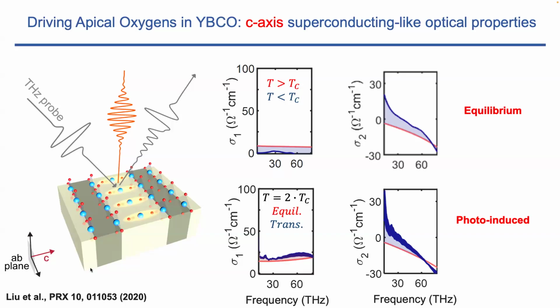in-plane electronic properties. This is the transition when you cool the material below TC in equilibrium. Along the C-axis, the material is insulating. Basically, there's very small conductivity in equilibrium, there are gaps, and the imaginary part of the conductivity diverges. When you're photoexcited, you get exactly the same divergence of sigma 2, indicating that you're creating a state that is similar to a superconductor.